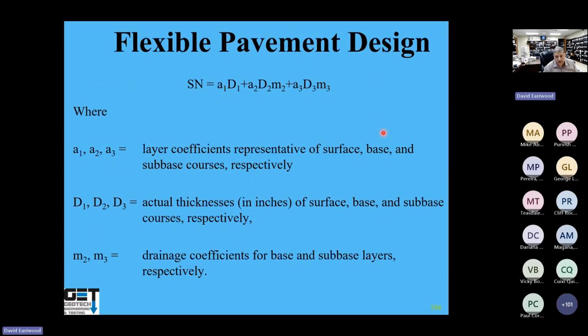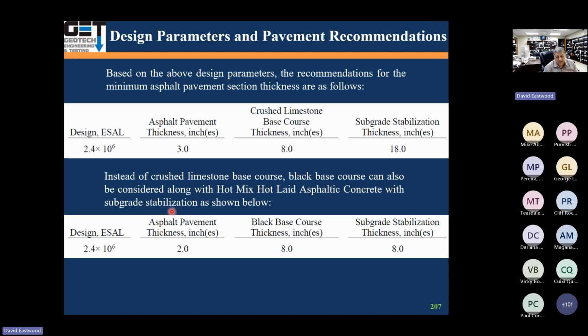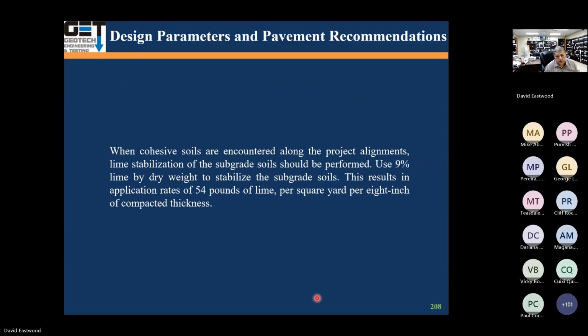So we go through this equation and come up with a proposed pavement design. One option, for 2.4 million traffic loading, is 3 inches of asphalt on top, 8 inches of crushed limestone base, and stabilization of the subgrade at 18 inches. Or you can reduce the stabilization with 2 inches of asphalt, 8 inches of black base, and 8 inches of stabilized subgrade. These are a couple of options. You can have a combination as long as your structural number is 4.2. All the cohesive soils on the subgrade, of course, have to be compacted with 9% lime in this case.